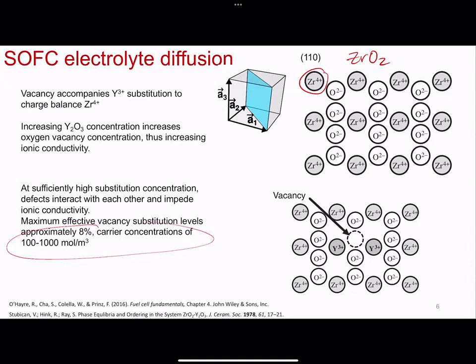And that is the exact mechanism for why you have high ionic conductivity, because you increase the vacancy concentration, which means you now have additional sites for O2 minus to migrate. When any ions migrate, whether you're in the lithium ion battery world, or you're in the ceramic O2 minus ion conduction world, the ion has to go somewhere. Whether it goes into an interstitial site, if it can fit there, or it goes into a crystallographic Wyckoff site, it needs a physical position to go into at the atomic scale, right? So if there's a vacancy, then it can occupy that space and then it can hop along. So when you increase vacancy concentration, you increase ionic conductivity. But there is too much of a good thing.